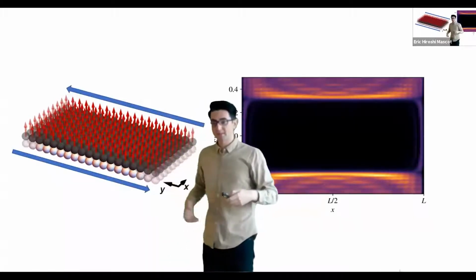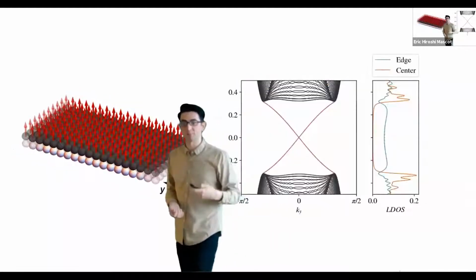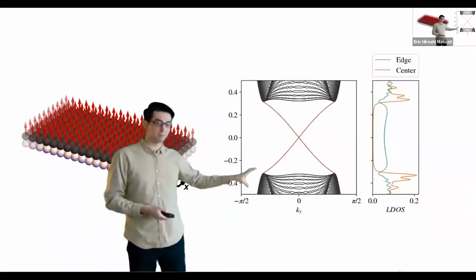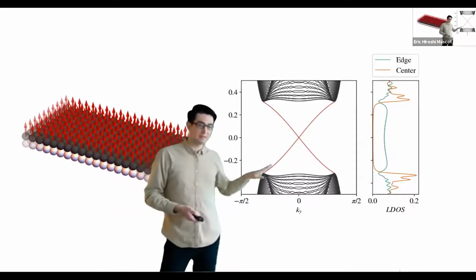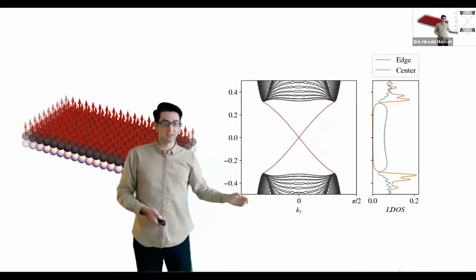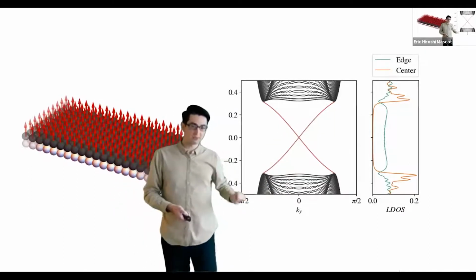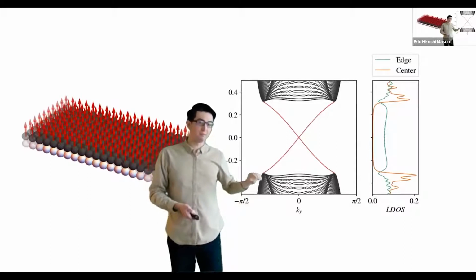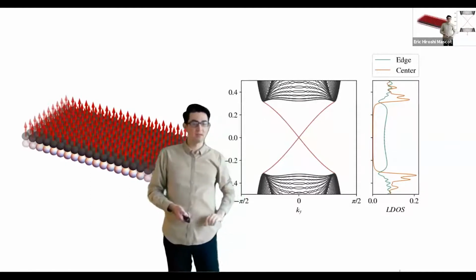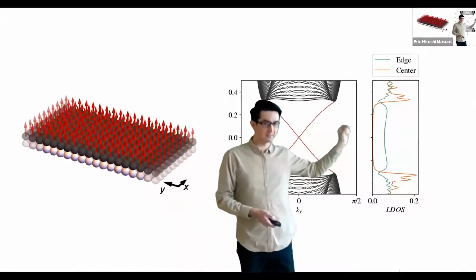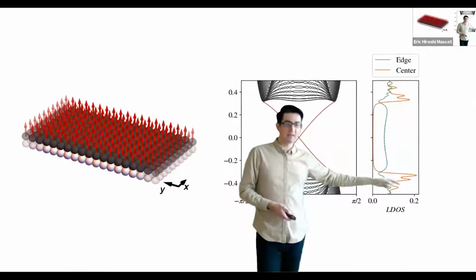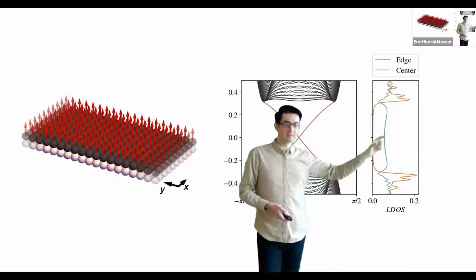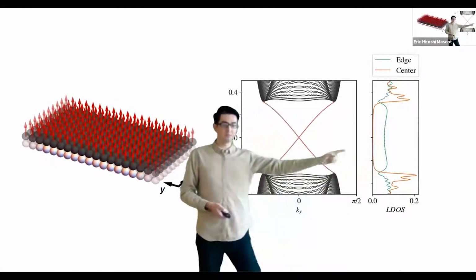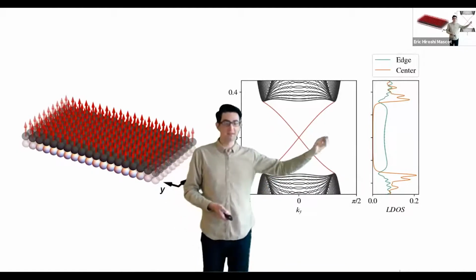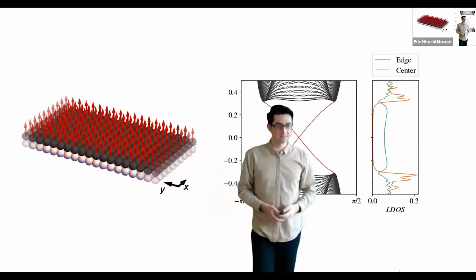And since this is a translationally invariant system, we can look at the dispersion of this. So here we have the bulk superconducting gap, and then this is the edge dispersion. And this is a topological edge dispersion because it connects this bottom bulk to the top that crosses the superconducting gap. And if we again look at the local density of states, the center of the ribbon has this superconducting gap, but along the edge, what we get is this flat density of states. And that comes from the shape of this dispersion. It's relatively linear, and so we get a relatively flat density of states.